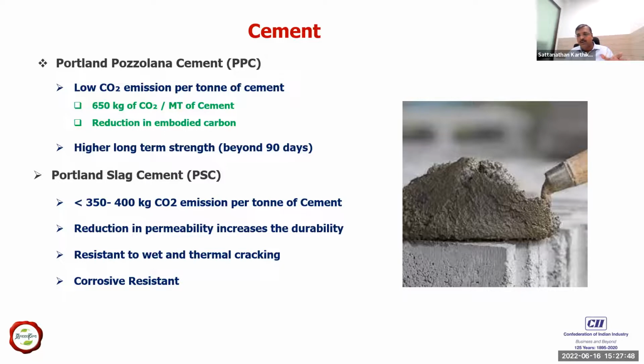One is ordinary Portland cement, which is supposed to be a very pure cement, and second is Portland Pozzolana cement, PPC as we call it, which has fly ash to the extent of about 35%. To that extent, the clinker requirement comes down, so the carbon footprint also comes down. For example, if you take ordinary Portland cement, the carbon footprint is about 800 kg per ton of cement produced. In case of PPC, it is only about 600 to 650 kg per ton of cement. So obviously the carbon emission is lower.